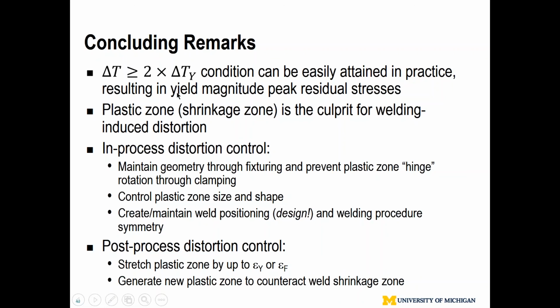So here's the key message: the most effective control of distortion is in process, because you don't have to overwork as long as you have the right procedure. That means, again, I already illustrated through various examples, you've got to use a fixture if you don't have good symmetry. Even if you have symmetry, you can use multiple welding tools, but the fixturing has to be properly applied to maintain overall geometry, just like this example. This one doesn't even have any symmetry. In the meantime, prevent the plastic zone hinge effect.